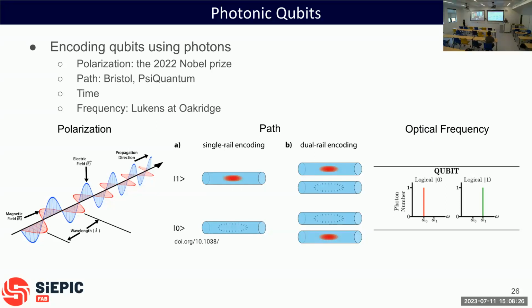I was really excited about this field, but probably the biggest problem is with the beam splitter. I mentioned our best beam splitter that we made has a 0.01 dB insertion loss, which is like 99.99% splitting efficiency. This is effectively a beam splitter where you can come in with one tone and split into two, right?